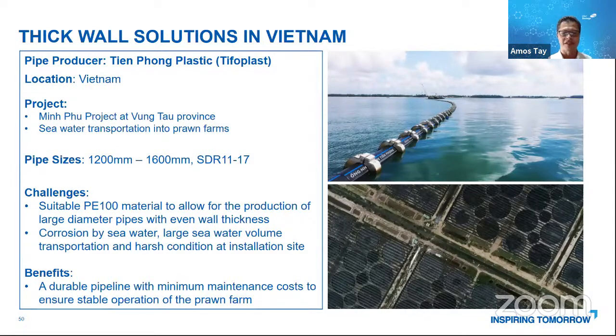Here is just an example of this material being applied. In Vietnam, the pipe producer is Tien Phong Plastic, or known as Tifoplast. They have this project, the Minh Phu project, for the supply of seawater into the prawn farm. The pipe sizes made were 1200 to 1600 mm, SDR 11 to 17. The wall thickness ranges from 94 mm to about 109 mm, which is a very thick wall.